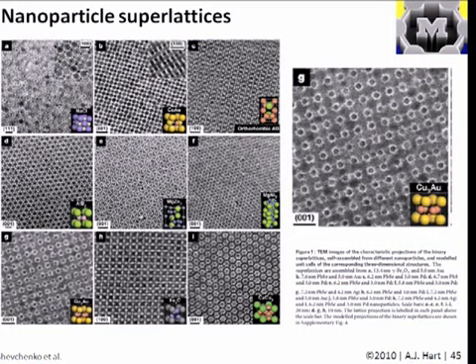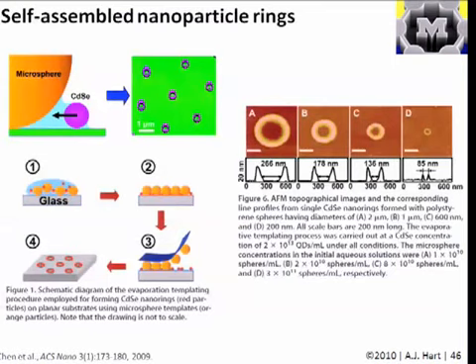And so as a corollary, for example, the self-assembly of these polymer microspheres has been studied very widely, but there aren't many good synthesis processes that can create highly monodispersed polystyrene particles beneath a diameter of, say, 200 nanometers. So as a result, there hasn't been a lot of success in packing polymer spheres having diameters less than 200 nanometers. And one big key in the work shown here is the ability of this research group to also make highly monodispersed solutions of, for example, iron oxide particles or gold particles, such that they can get them to pack in this interesting and ordered fashion.